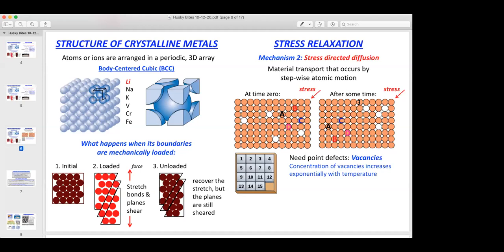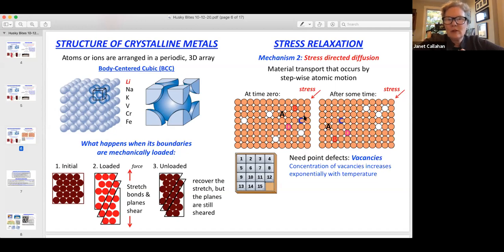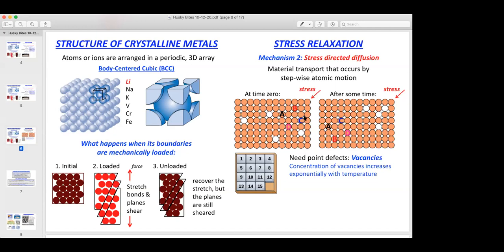The stress creates a gradient in the chemical potential that drives the migration of the vacancies into the stressed volume. Clearly, in order for stress-directed diffusion to work, we need vacancies. If you take the vacancy away, the mechanism becomes completely inoperable — the game just doesn't work anymore. The concentration of vacancies is exponentially dependent on temperature, so the higher temperatures you go to, the more vacancies you have to enable this stress-directed diffusion mechanism. Because they're vibrating more and more — it just makes it a whole lot easier for these atoms to move around.